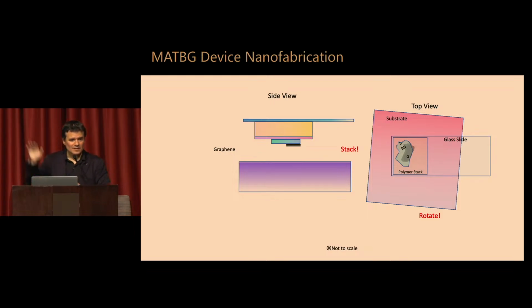And amazingly, I'm able to form this very regular moiré pattern, and continue doing processing to make a microelectronic device with this. This thing is very simple. A high schooler that comes to my lab learns it in a couple of afternoons, okay? But it takes quite a bit of dexterity. If you try to do it on your own without having practice for a year, without having someone teach you, it's not so easy. Because in reality, this is like taking plastic wrap, putting it on your kitchen table, one layer, without a single wrinkle, and then you tear half of the plastic wrap without a single wrinkle, and put the other one 1.1 degrees on top without a single wrinkle, okay? So it requires perseverance, and my students have golden hands, so that's great.